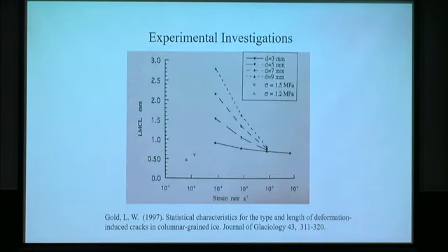I guess this is a similar thing. We are looking at the crack size or the crack length versus the strain rate, for various grain sizes. The higher the strain rate, in this case, there is a tendency for smaller cracks to nucleate.